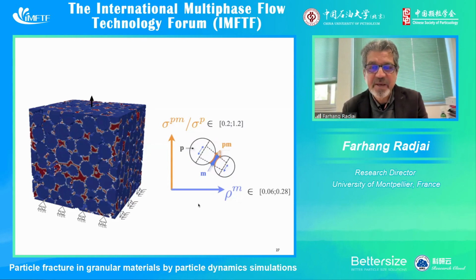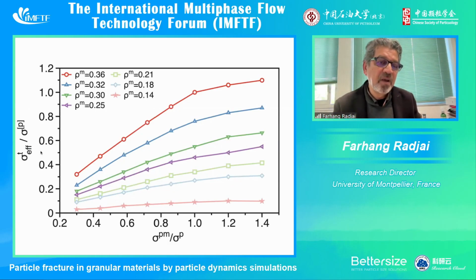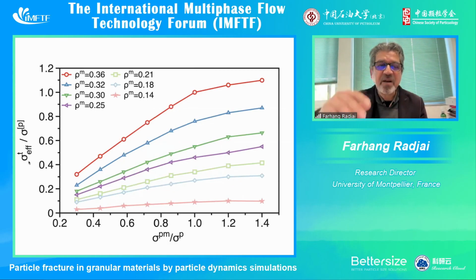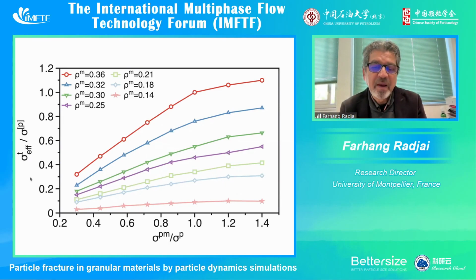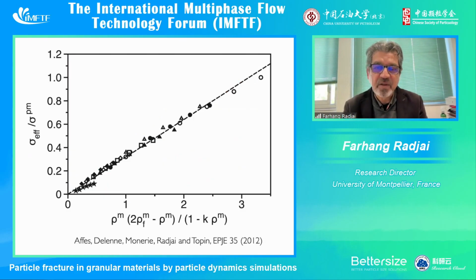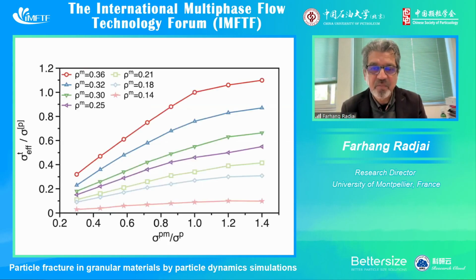So this is our parametric space. And here you see, for example, when we apply it to a volume element of the material, the tensile strength in simple tensile loading as a function of interface adhesion, sigma PM. P is for particle, M is for matrix. So you can see that for different amounts of the binding matrix, the strength increases with the adhesion, in a nonlinear way. But we can, of course, scale the data. So there are ways to scale the data and produce from all these curves a single one. This is not the point here.